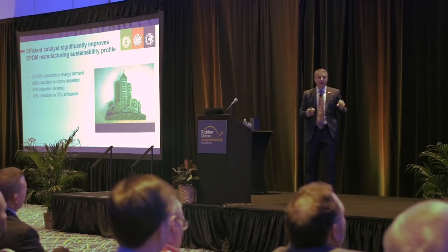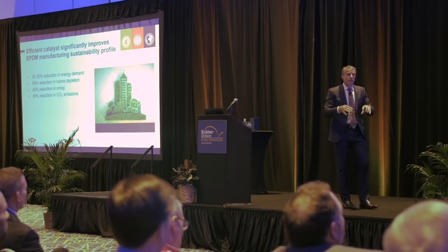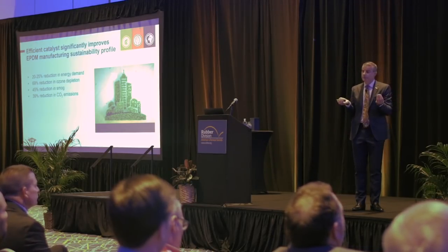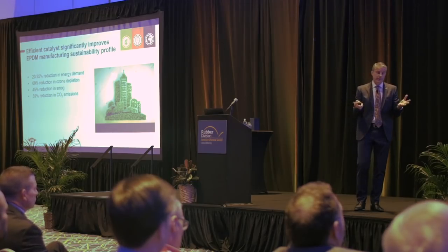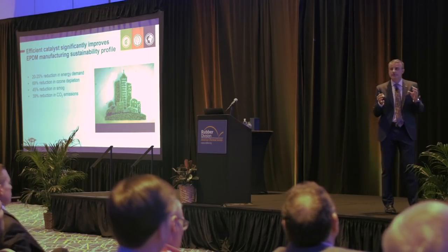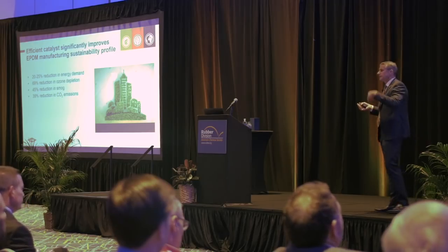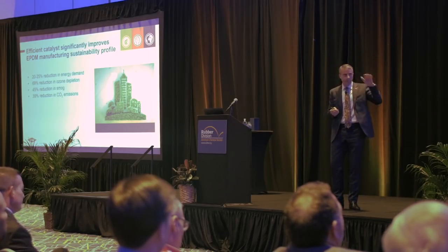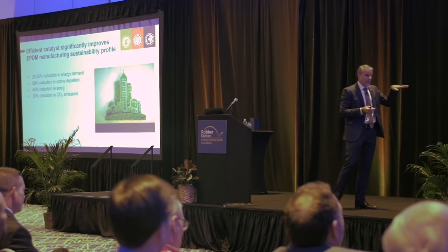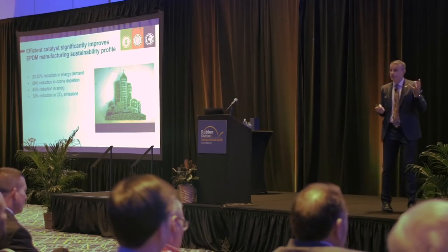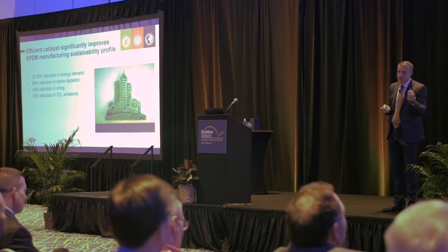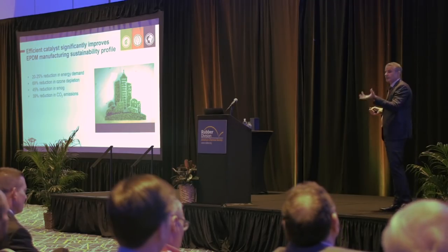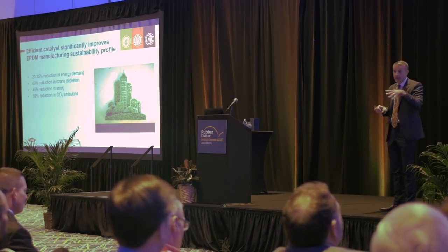But this process not only gives you more control of the final properties of the elastomer, it is also much more sustainable. You can run this at high temperature, and it makes it much more efficient in terms of molecular weight gain. The classic Grignard approach leads to a lot of side products, salts, metals, and so on that you had to wash out, and that you don't have to wash out anymore.